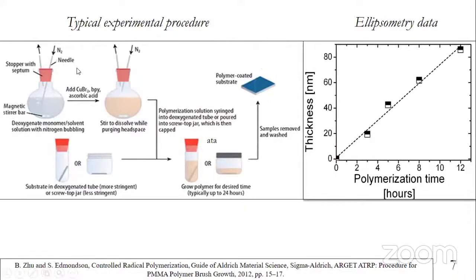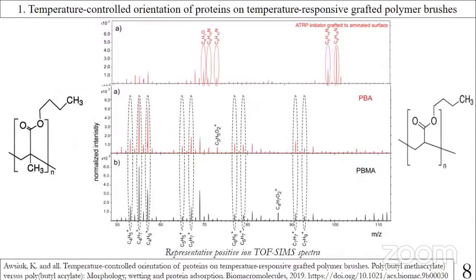In a flask, methanol, water, and monomer are mixed and deoxygenated by bubbling through nitrogen for 10-15 minutes. Add catalysts, and the headspace is purged with nitrogen again. The solution is transferred over the substrates in the deoxygenated tubes. And after the desired polymerization time, samples are removed and washed with methanol and water. And typically, this method produces a polymer growth rate of approximately 5-10 nanometers per hour.